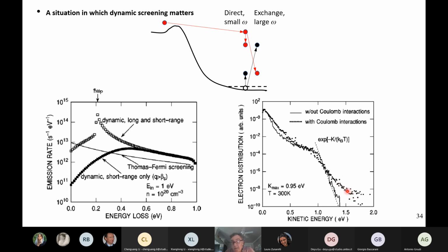And this can lead to interesting details that people are worried about. One typical issue due to this effect is how come people dealing with silicon-on-insulator field effect transistors were seeing impact ionization at a drain bias which was way less than the band gap of silicon. You expect impact ionization to occur, we'll talk more, at the band gap, of course actually higher because of momentum and energy conservation. But at the minimum, even if ignoring momentum conservation, and I'll tell you why there is a reason to do so in some materials, you would expect no impact ionization to occur at 1 volt. An electron can be degenerate in the source, has an energy around 1/10 of an electron volt. By the time it gets to the drain, it will have the applied VDS, 1 volt, plus the initial energy, 1.1, and can impact ionize.